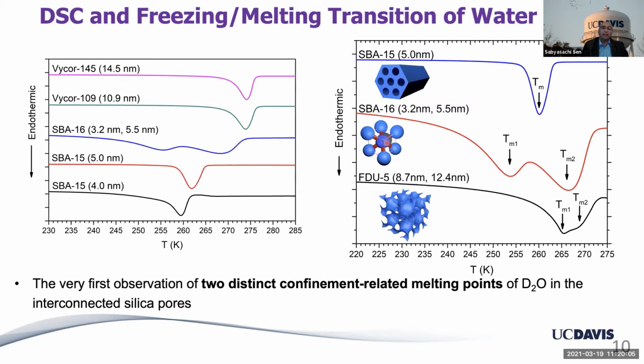If they would be freely exchanging and diffusing, then there should be just one melting point, but instead we can distinguish two melting points, as if water in the cylindrical pore does not talk very efficiently with the water in the larger 5.5 nanometer spherical pore. They can diffuse eventually, but over the time scale of the DSC measurement, you can clearly pick out this strong heterogeneity in the dynamics that would otherwise homogenize the melting and freezing behavior.